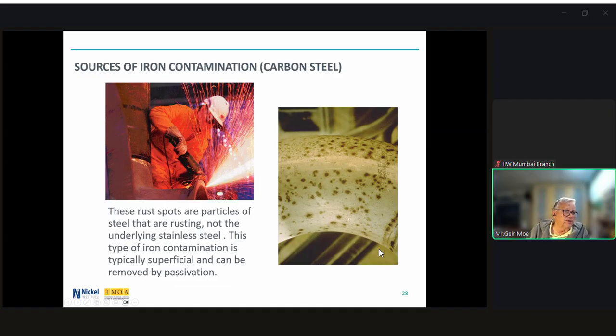Grinding on adjacent carbon steel can cause carbon steel particles to land on stainless steel surfaces. In this photo, these rust spots are particles of carbon steel that are rusting, not the underlying stainless steel. Though premature pitting corrosion may occur in these areas in an environment where chloride ion is present. This is the primary reason for passivation after fabrication, the removal of carbon steel particles that may have landed on the stainless steel.